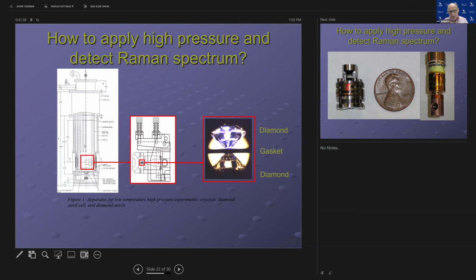It literally consists of two diamonds. You can see them there. And there is a gasket that has a small hole. The hole is about 200 microns. You have to get your very small sample, about 20 microns across, and put it in the hole. Put little pieces of ruby that you can use to measure high pressure. Then fill this with an inert gas such as helium and close this, basically apply force to those diamonds so that they create so-called hydrostatic pressure.